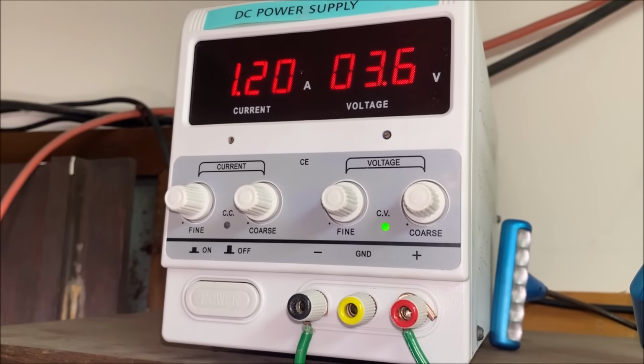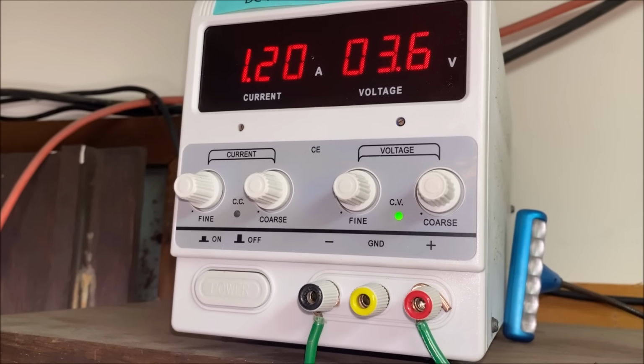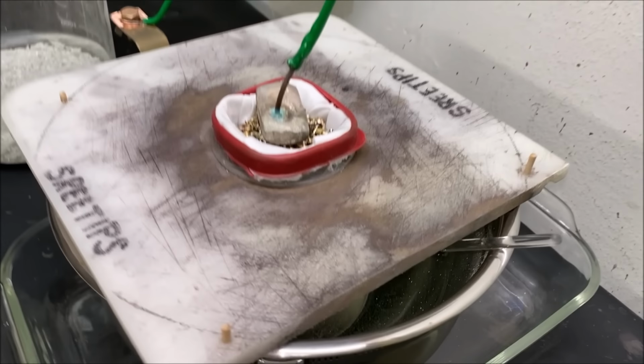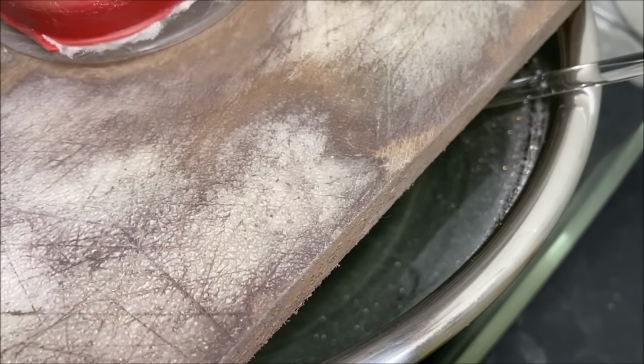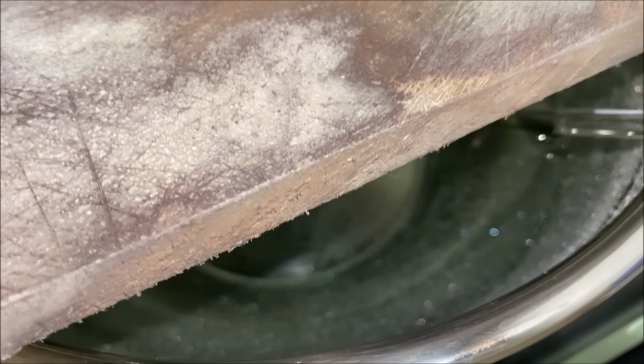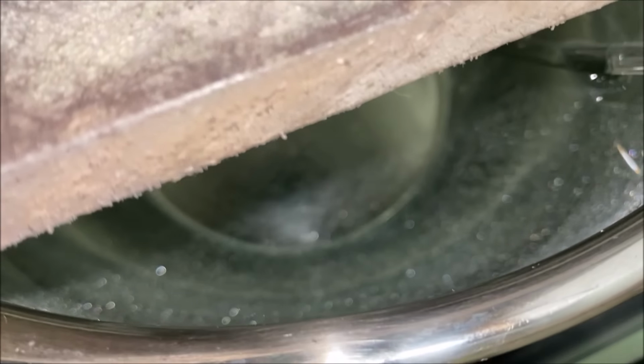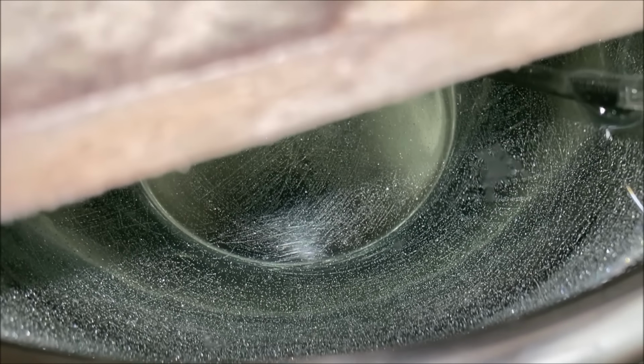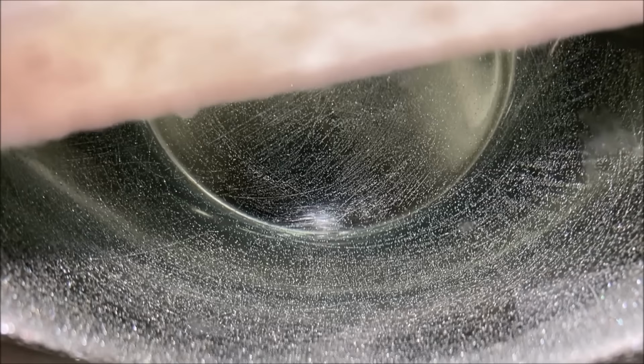I've got the power supply straightened out now, and if you look down in here, it's been running for about a half an hour now. You can see there's some pure silver crystal starting to form on the inside of the cathode down in there. This cell produces about 5 troy ounces of pure silver per day. That's about a half hour's growth right there.